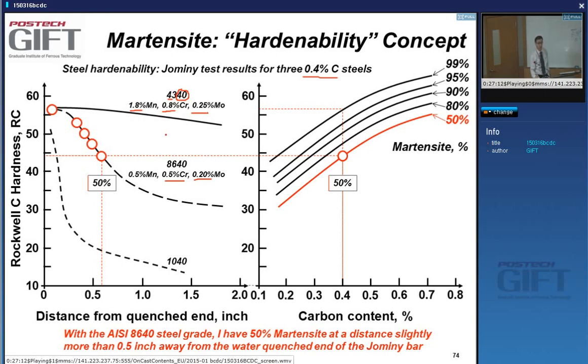Yes? And you can see that if you measure the hardness, this is a Rockwell C hardness scale, as a function of the distance from the quenched end, you see that all of them are martensitic at the surface of my Jominy test, because I have very high cooling rates. However, as we go away from the quenched end, the cooling rate decreases, and the unalloyed steel is very sensitive to this. The cooling rate is too low to get hard martensite formed away from the quenched end,